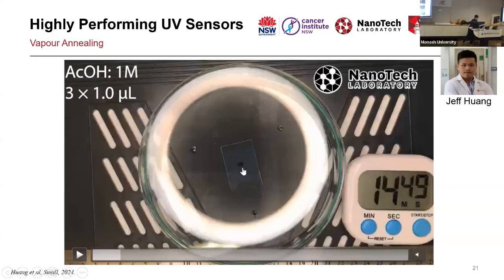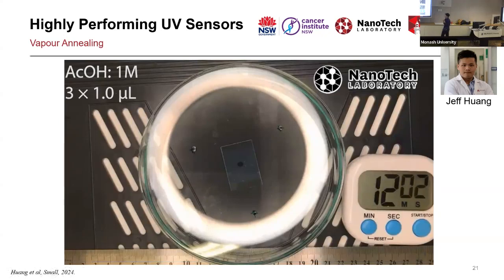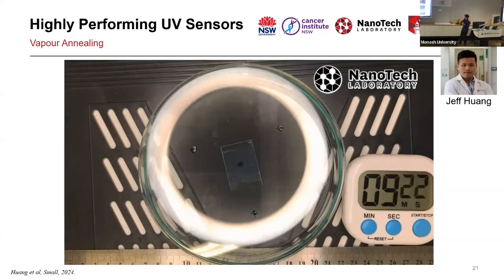What I want you to pay attention is how transparent it is at the beginning, and this is 15 minutes exposure, and I want you to have a look at how the transparency is changed after exposure to 15 minutes of 1 mole of acetic acid, which actually is only 3 microliter if you combine the droplets. So you can see that the transparency is changing significantly, which we assume is happening because the film is shrinking a little bit, and now the porosity is going to be less than what it was before. See how significant the transparency change over 15 minutes.